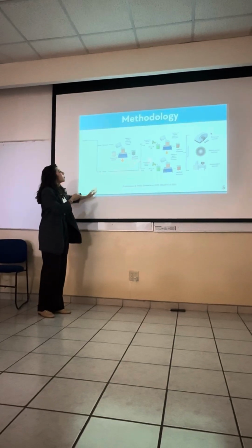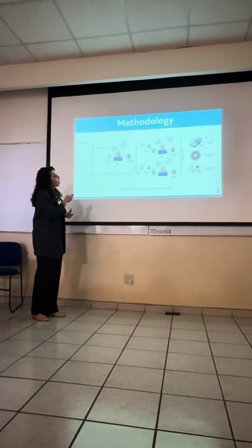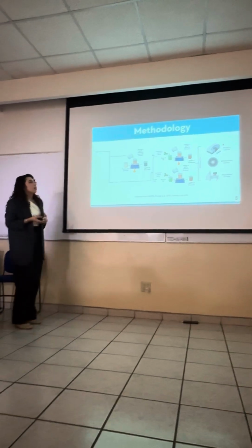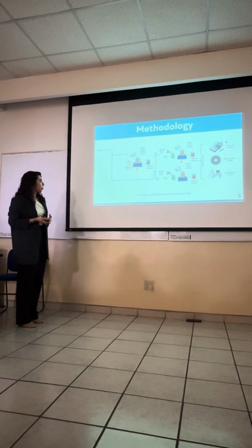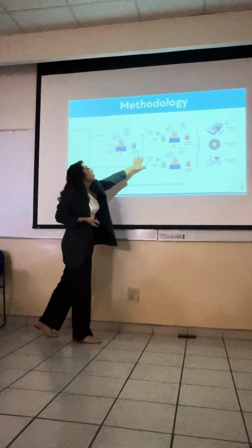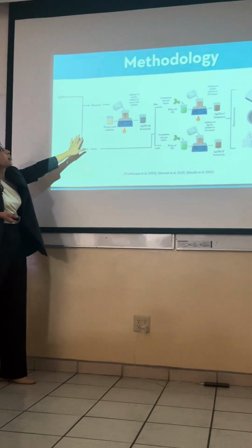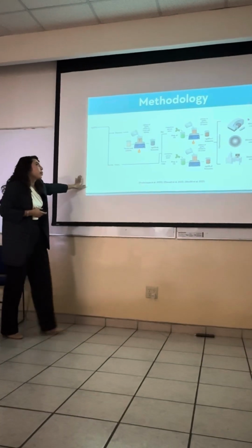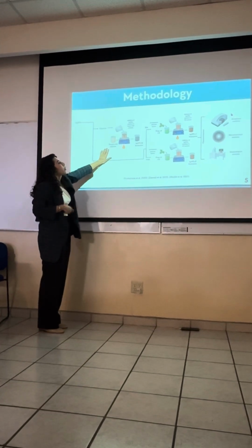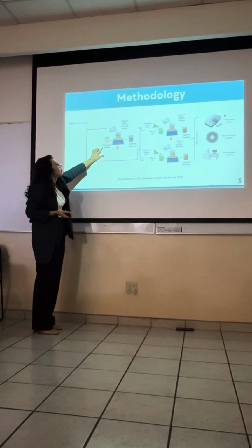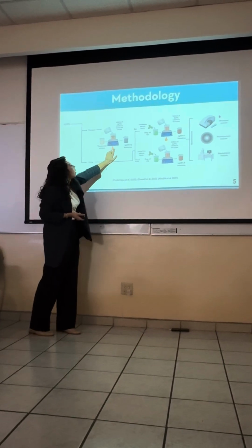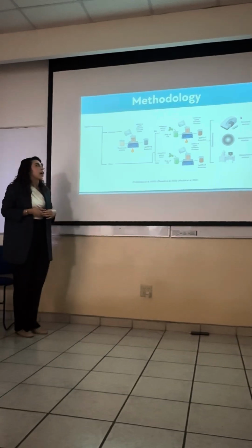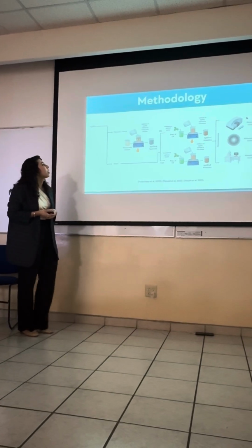The green one we subdivided into a hot method and a cold one, which was done under room temperature. For all three synthesis methods, we used silver nitrate as our silver precursor. For the chemical method, we used tannic acid solution as our reductor and stabilizer, whereas for the green methods, we used Coriandrum sativum extract, a plant extract.